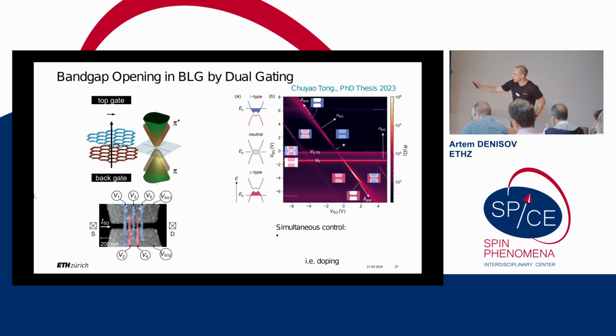Since we have two gates, top and bottom, we have control both on the size of the open gap, but also on the electrostatic doping, meaning that we can shift the electrostatic potential up and down. Usually the first plot we acquire after the device is made is the so-called gate-gate map, where we plot conductance through the channel as a function of backgate voltage and split gate voltage. This diagonal line, you can see, is aligned with a really high resistance, so almost no current is flowing through the channel, meaning that the channel is pinched off. So by parking here, we know that we can start tuning our quantum dot further using this thin finger gate.